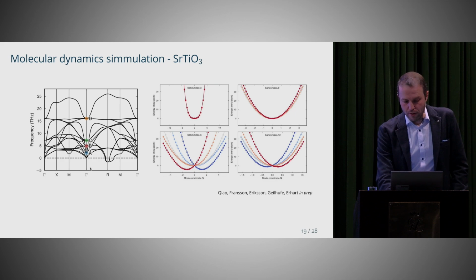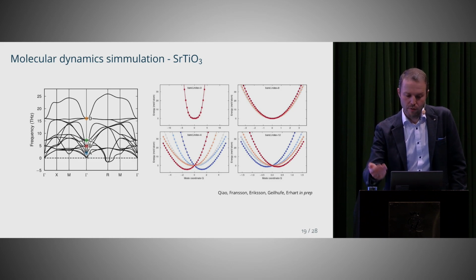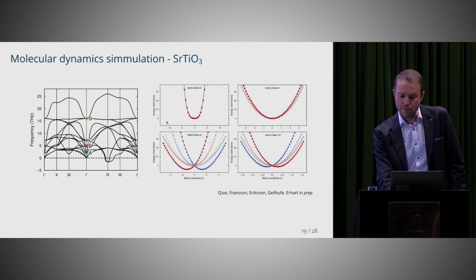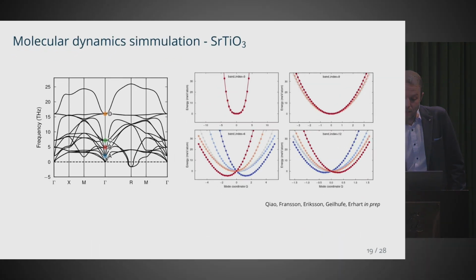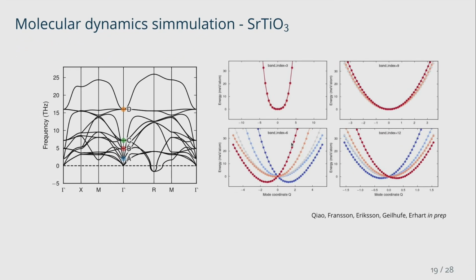To the left, you see the so-called phonon band structure. It contains a lot of these spaghetti lines. So each line corresponds to a very specific mode with a very specific frequency and so on. But there are 4 modes which I highlighted, and 3 of them are modes that one can talk to with a laser field. And basically those modes start to couple to each other, and that is what I'm showing to the right. So if we think of driving the B mode, the A mode, then we can see that there are basically 2 modes that are very strongly affected, and 1 mode which basically doesn't do anything.